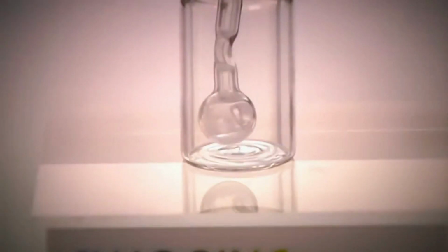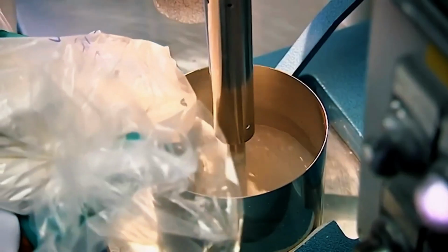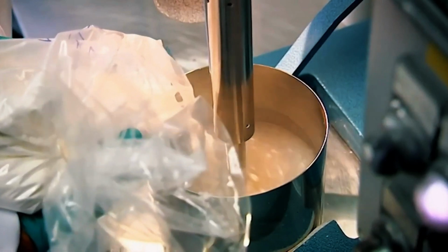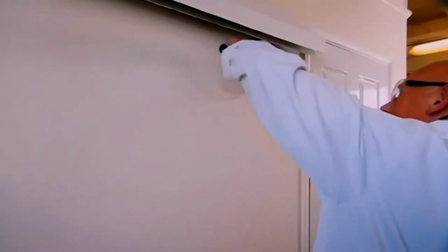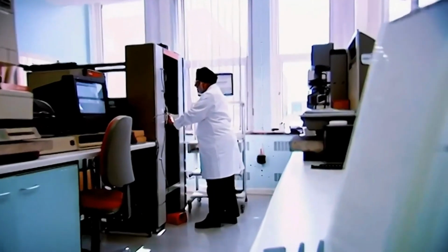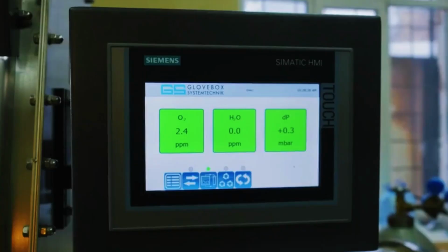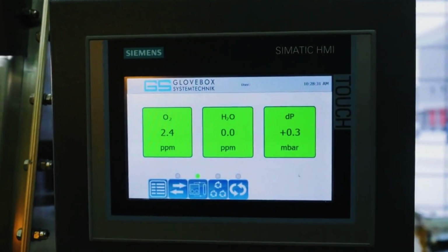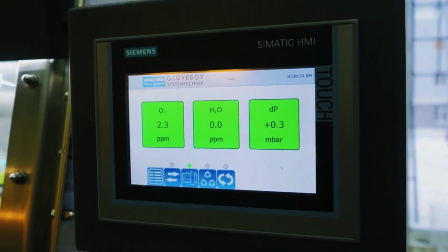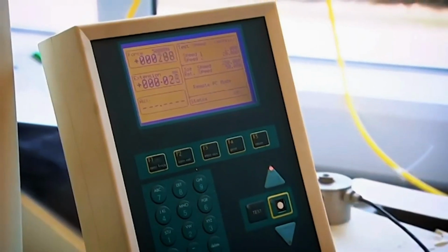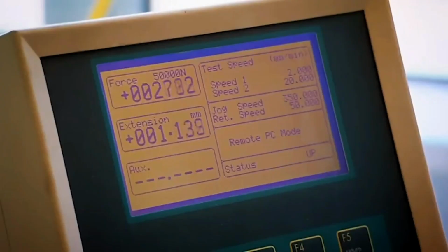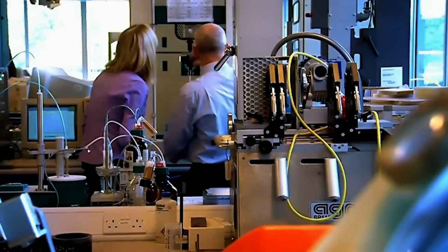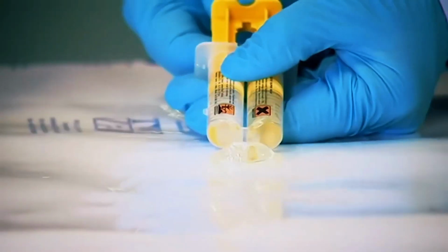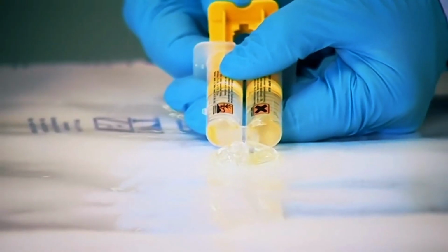The mixture then passes through homogenizers that act like giant beaters, dispersing everything uniformly with no clumps or texture variations. At this stage, controls include rheological analysis, which measures how the adhesive flows under different conditions, and strength tests performed with dynamometers capable of applying stresses up to 25 megapascals. To put that in perspective, this force is equivalent to holding up a small car with nothing but a properly made adhesive bond.